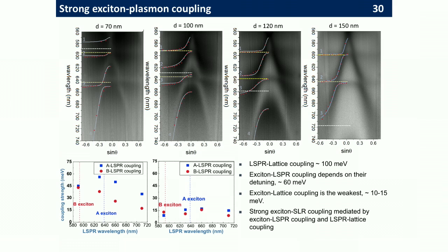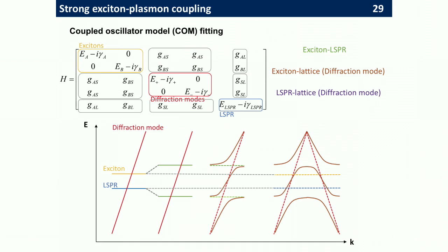Polaritons. An interesting thing is that by changing the geometry of the system, the size of the particle or the spacing between the particles, we can tune the exciton-plasmon coupling strength quite significantly. So it's a tunable system that we can create. This is basically what is happening. We have the exciton, which is flat in dispersion. We have the surface plasmon, which is flat. Then they can hybridize and create these new states, but still flat.